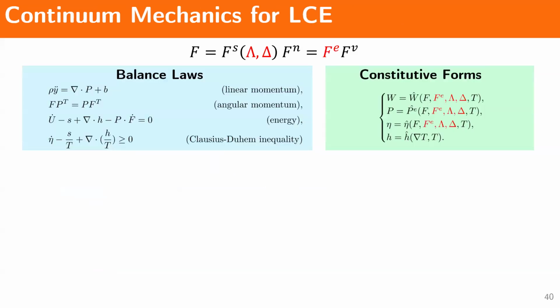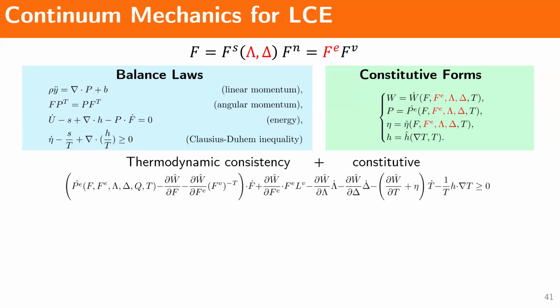Now we're going to invoke the continuum mechanics recipe for these liquid crystals. We assume again the following decomposition of our deformation gradient, and then we have our regular balance laws. This is the typical balance law, and we postulate the following dependence of our free energy, where now we have the two internal variables from the equilibrium case, and we also have an additional internal variable because we have to take into account this rate sensitivity effect. Physically, this means the elastic instantaneous response of the polymer network. So we can combine the two energies with the balance laws, and this lands us at our dissipation inequality.